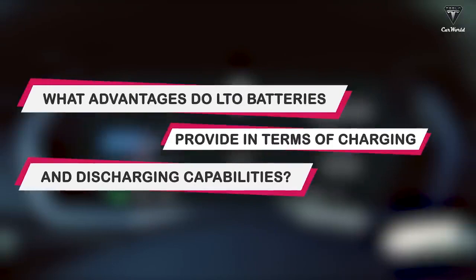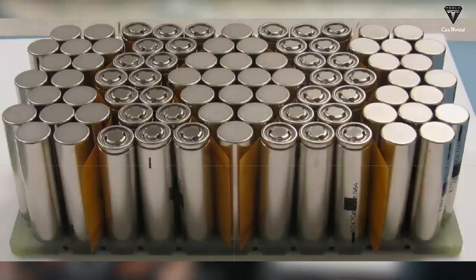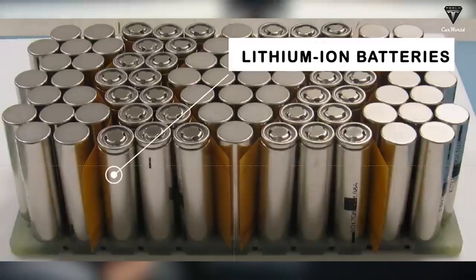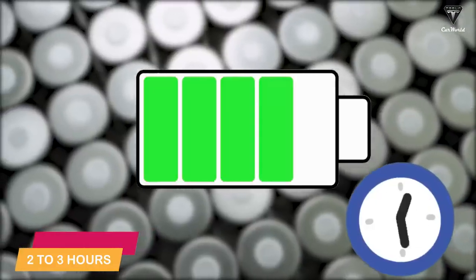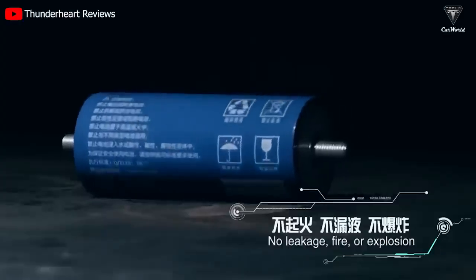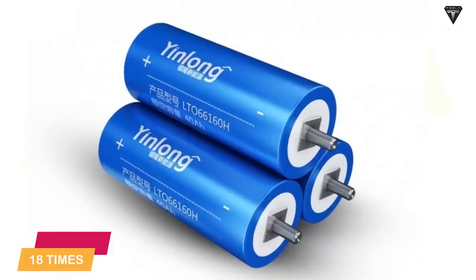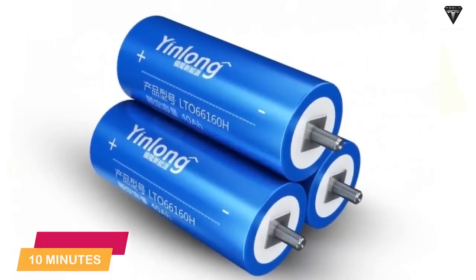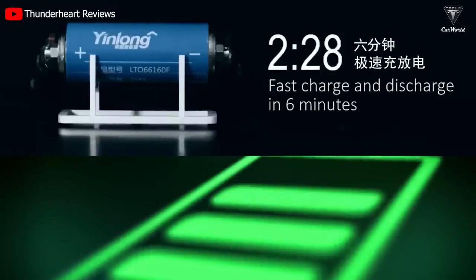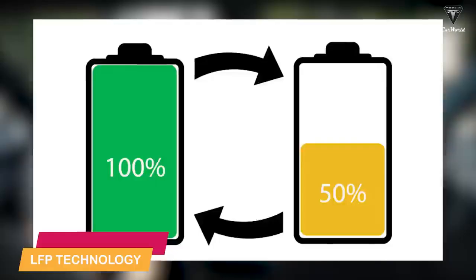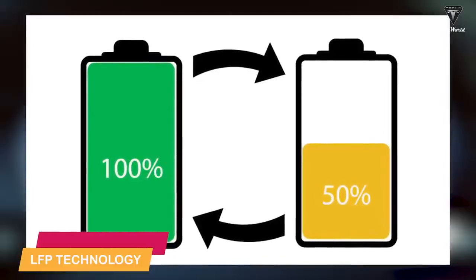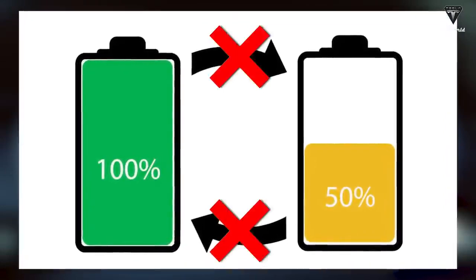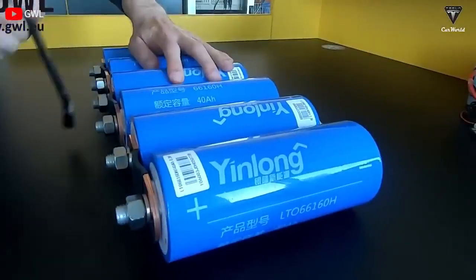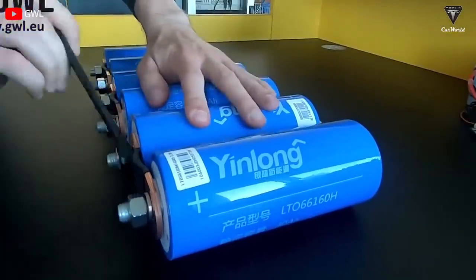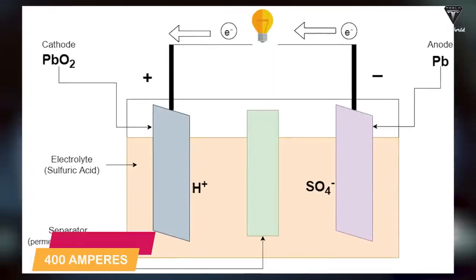Next, what advantages do these LTO batteries provide in terms of charging and discharging? When compared to traditional lithium-ion batteries, they take about 2 to 3 hours. But the LTO battery can be charged 18 times faster in 6 minutes. LTO batteries are the sole option for high-speed charging because LFP technology does not permit continuous high-speed charging and discharging. The maximum charging and discharging current for this battery is typically 10 C, which is 400 amperes.